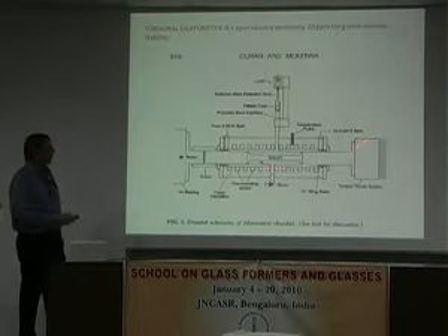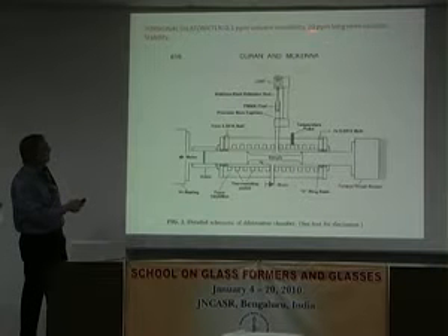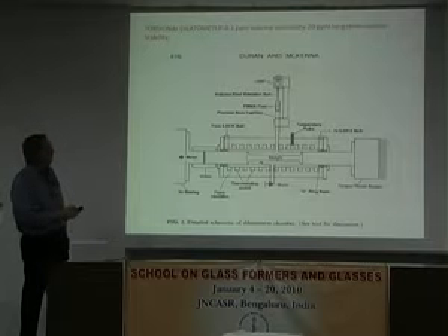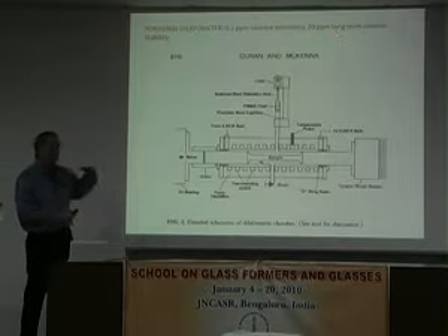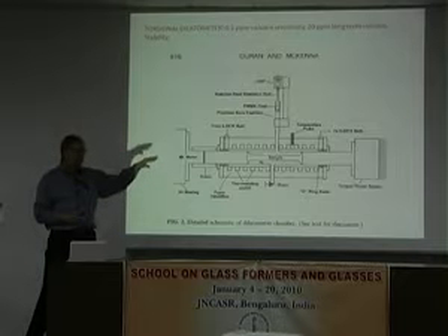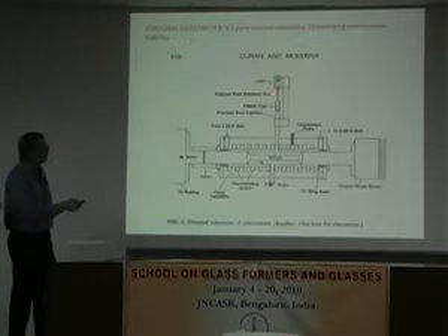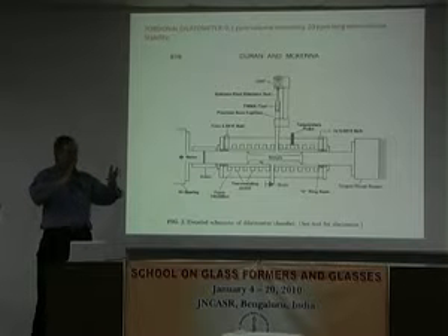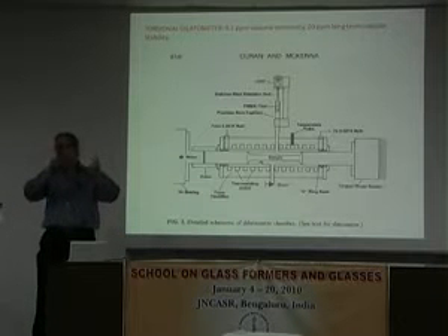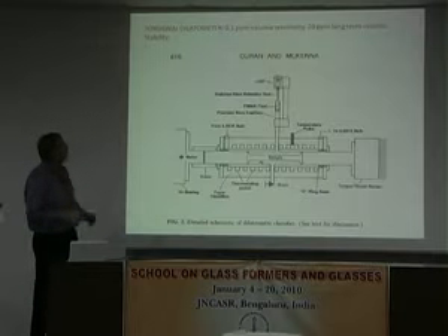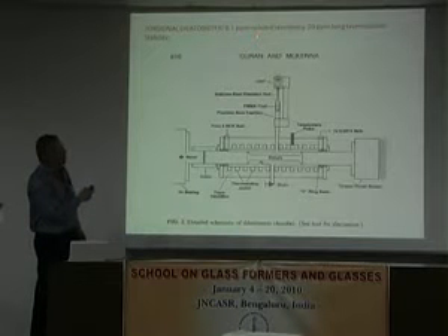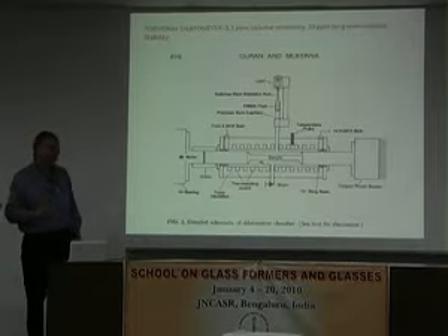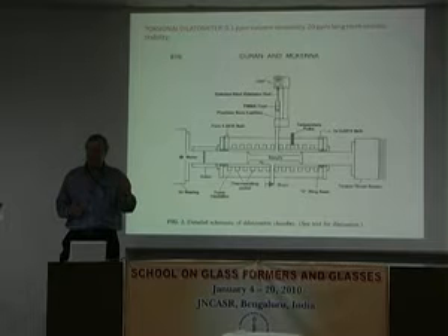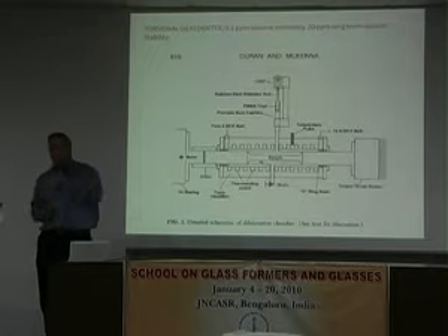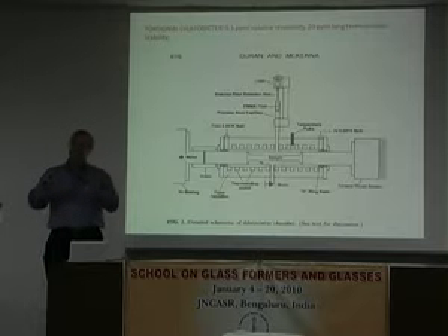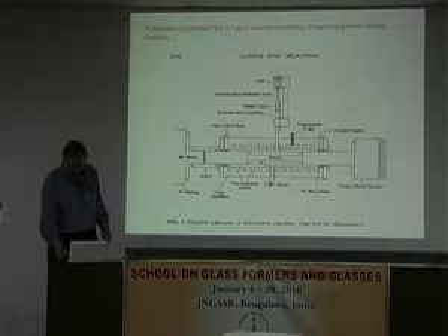And when we get done, the fact is, long time, because of the volume changes primarily in the mercury, we're limited to 20 times 10 to the minus 6 long-term resolution or stability in the volume change, so 20 parts per million. However, instantaneously, in the mechanics part, we can twist the sample in less than a second. So we can twist it, and instantaneously, we could actually measure 0.1 part per million in the volume due to the mechanics, okay? So now we're going to ask what happens if I compare the volume recovery after a temperature jump when I do either twist and untwist, or I don't do twist and untwist.